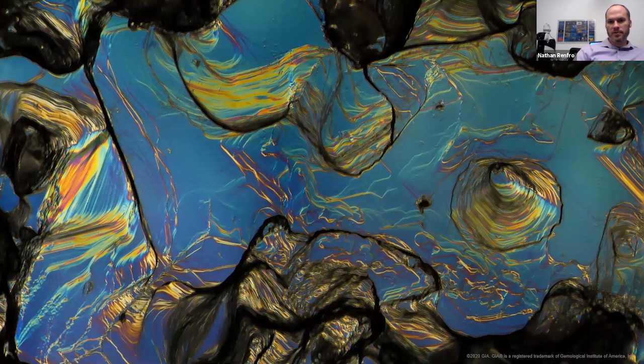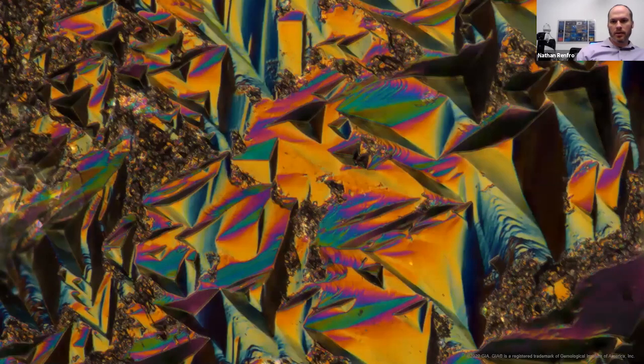Here's another image looking along the basal plane of one of these sapphires — this one is from Eldorado Bar or possibly Rock Creek, and either way they both look pretty similar in the microscope. What you see is a nicely etched surface with no rounding or abrasion from water transport. Corundum is a trigonal mineral, so when we look perpendicular to the c-axis, we see the trigonal symmetry of the corundum crystal itself in these etched triangular shapes that we call trigons.